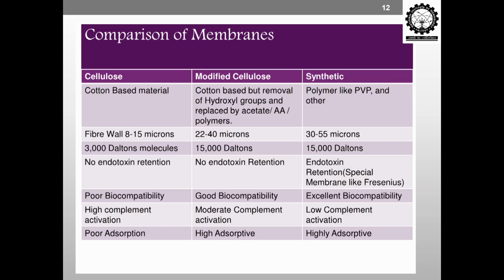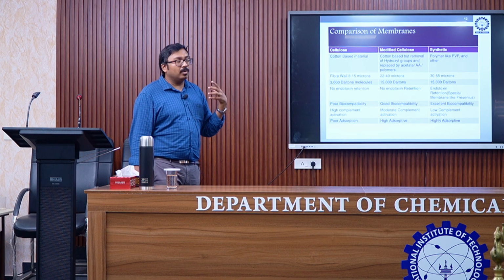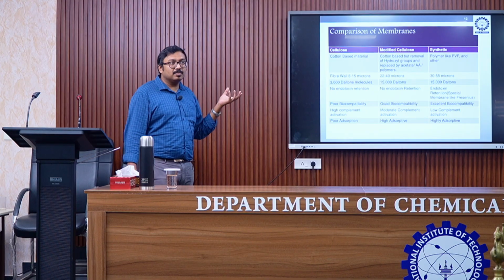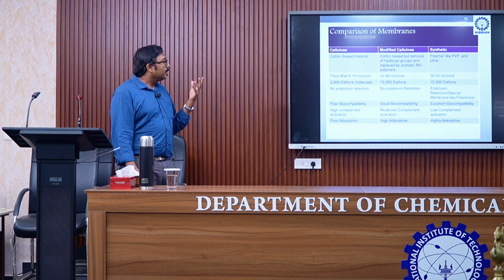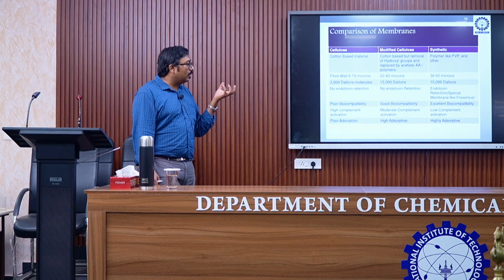So if you were to compare the different materials, cellulose and modified cellulose were initially used for the membranes, and they were very good in the sense that the modified cellulose had good biocompatibility. The sizes and the wall thickness were smaller, and they could retain solutes greater than 15,000 Dalton, whereas any uremic solutes that are less than 15,000 could be cleared by the membrane. However, it could not capture endotoxins.